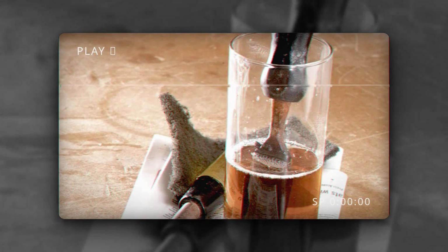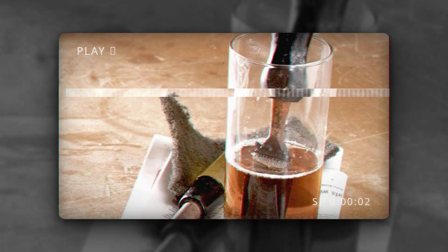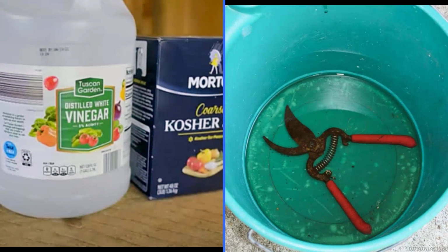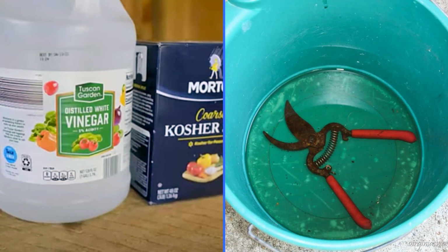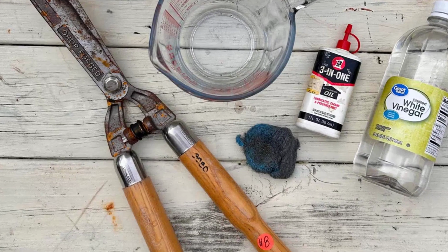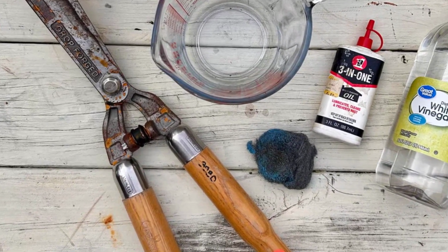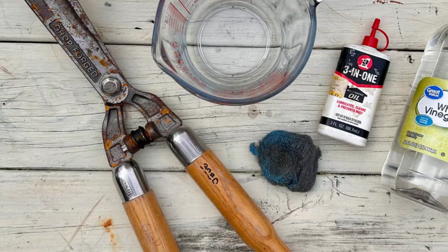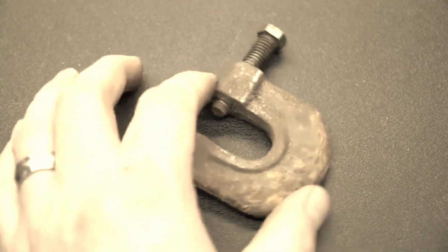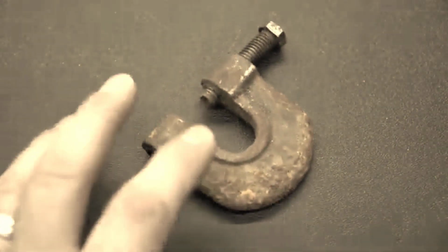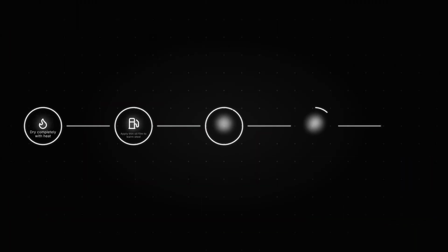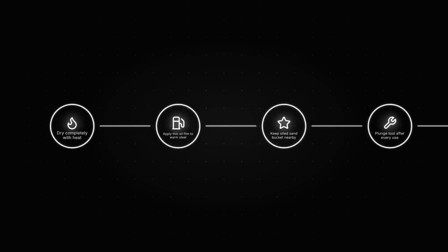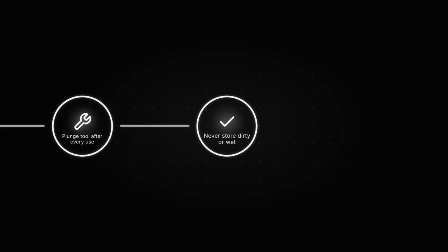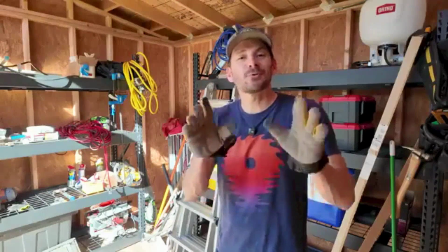So, the whole sequence. Degrease the tool, then submerge it completely in white vinegar at room temperature for 6 to 24 hours, lifting it out every few hours so the acid keeps reaching the metal. Neutralize it in baking soda and water for 10 minutes and scrub the black layer off with nylon. Dry it immediately and completely with heat, then wipe a thin film of camellia or mineral oil onto the warm steel. Keep a bucket of oiled sand by the shed door and plunge every tool into it after every use. And never put a tool away dirty or wet.